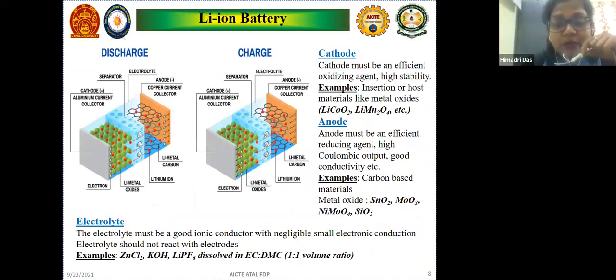Here let me explain the mechanism of what is actually going on in batteries. So I'll just give a gist. In a battery, as we know, we are using two electrodes, cathode and anode. Here in a lithium ion battery, the cathode is usually a lithium based cathode like lithium cobalt oxide or lithium manganese oxide or lithium iron phosphate. Similarly the electrolyte is also lithium based, like LiPF6 with some solvent, and then anode materials like graphite or other anode materials like metal oxides and all.